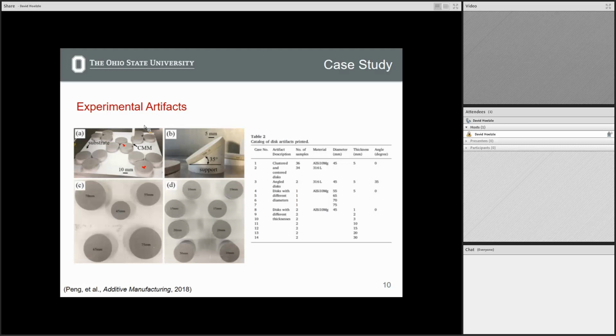And then, looking at what we did here, we had a lot with an angle of 0, so that's what you're seeing right here. We had a few that were printed at an angle, just to understand what happens when you print at an angle. And then we looked at changing the diameter. That's this plot here, this is 45, and then we're going up from 45. And then we also looked at changing the thickness. This image is not so good for understanding the thickness, but we're going from a thickness of 1 millimeter all the way up to 30 millimeters, so very thick parts. This is getting to where the thickness is on the order of the diameter of the part. It's getting to be more regular, with the same dimension in each direction.